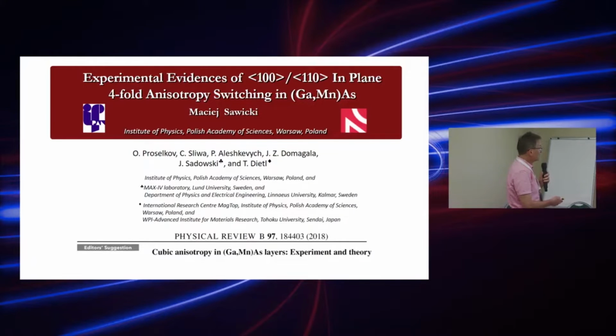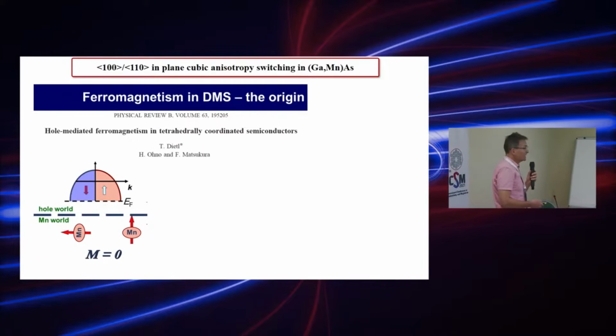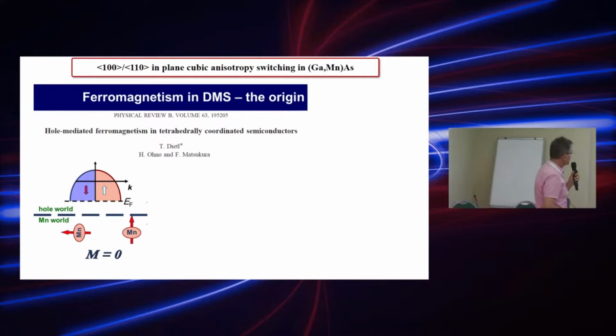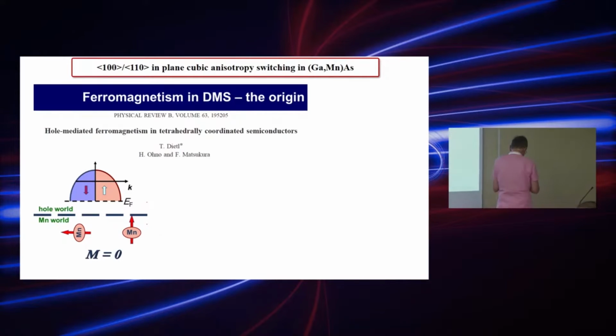So before we proceed to the subject, let me just say a few words about the origin of ferromagnetism in this material, because this is very important to understand why the feature I'm going to talk about is so important. In order to understand how the coupling or the ferromagnetism is possible in this material, we can start from treating our mixed material as 2 independent worlds. One is the semiconductor basis, which is p-type. In this case, this p-type gallium arsenide, and the holes are actually brought about by manganese atoms which are there.